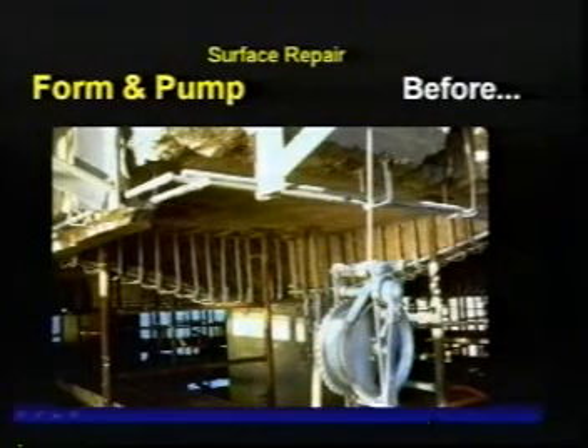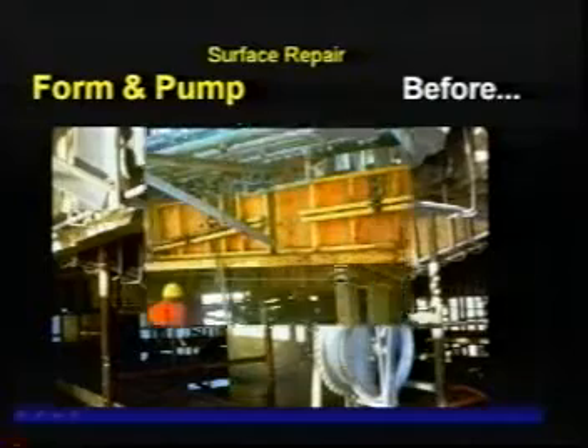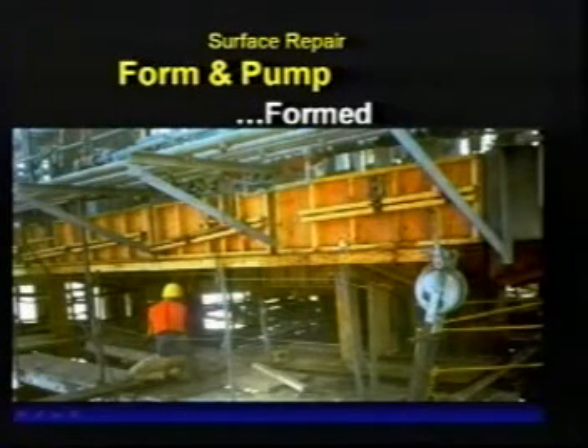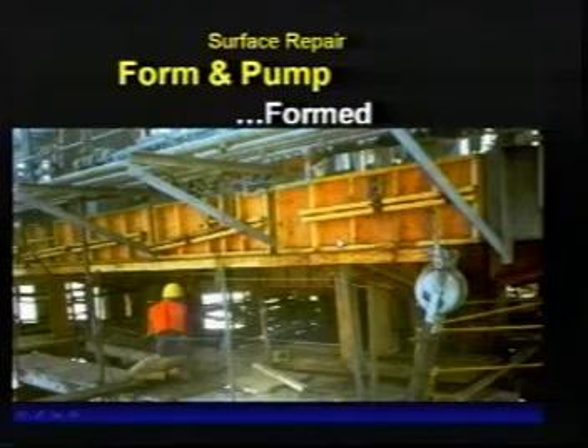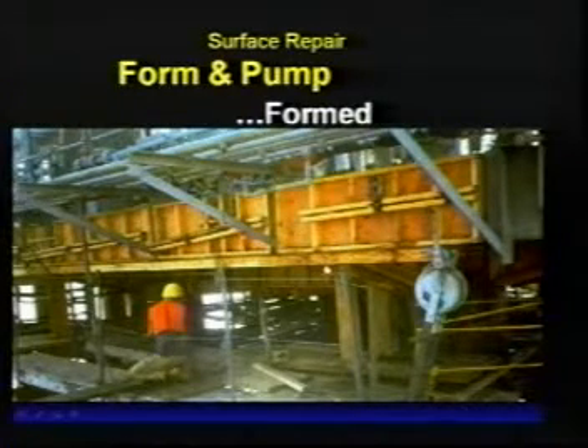Now this is an example of another application using this technique. This is an offshore platform out in the Gulf of Mexico, and this particular structure was subjected to the salt exposure of the seawater, and over many years deteriorated. So the concrete's been prepared. Formwork's installed, and we use the same technique where we're actually site mixing, or basically a ready-mix concrete on barges, pumping it into these forms.